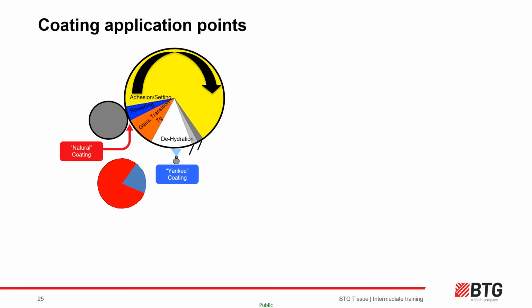If we now consider the addition of natural coating or process contamination to our coating model, Yankee applied coating is the blue segment and applied at the spray bar, with the red portion being the coating contamination inherent in the wet sheet presented to the press nip.